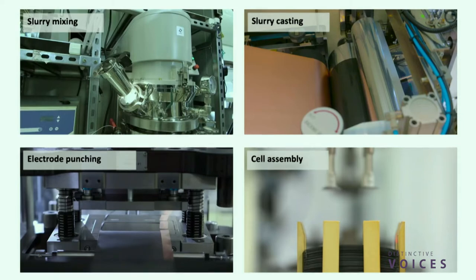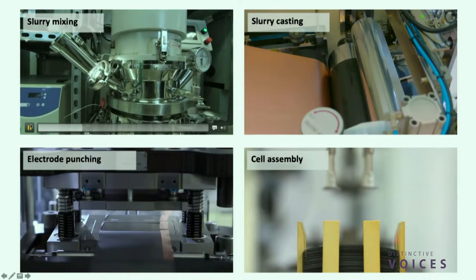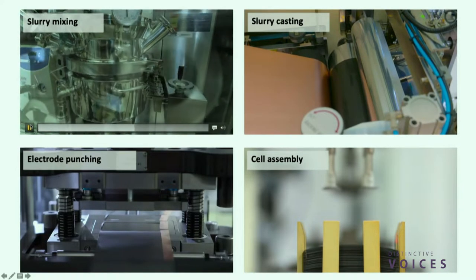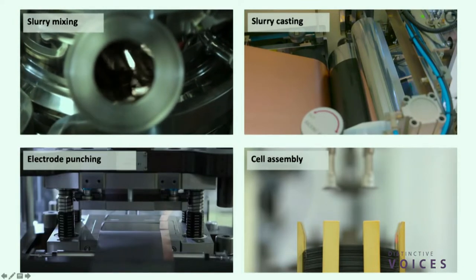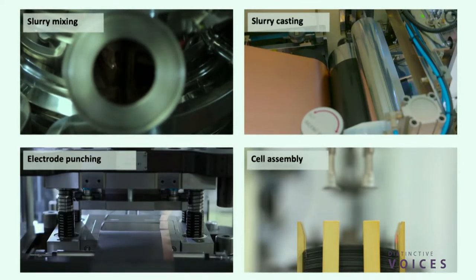Okay, so just really quickly, this is something that I'm very privileged to work over. My laboratory is directly over the University of Michigan Battery Lab. At U of M, we have this pilot line facility where we can make these batteries. And just really quickly, how are they made? I'll show you in four squares. You make a paint with an anode or a cathode. You mix it with a certain solvent, a certain binder, it's like a Teflon derivative.